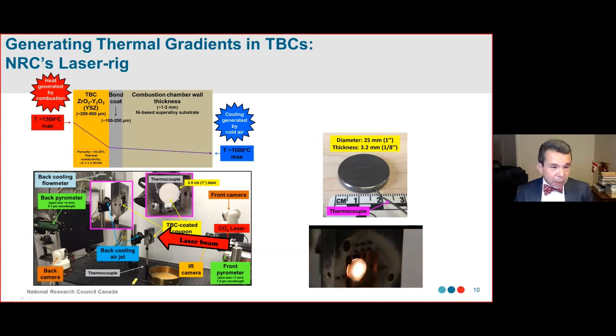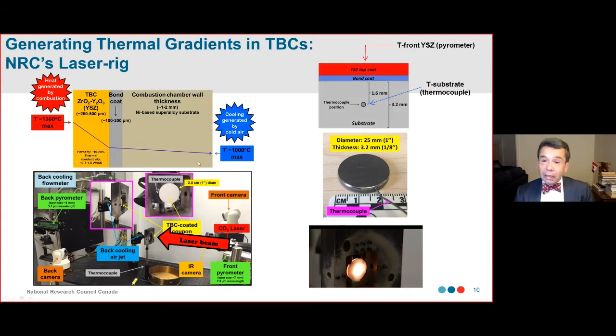And when you look at this picture, you can see there is a nozzle in here. This nozzle has compressed air at room temperature that keeps flowing over the backside of the substrate. This backflow basically cools the system, and therefore we generate a thermal gradient and we can study TBCs. How we study them: we measure the temperature of the YSZ or ceramic TBC using a pyrometer, and we measure the temperature of the substrate using this thermocouple here. This distance is about 1.6 millimeters, and I have been telling you that the thickness of these walls is between 1 and 2 millimeters. So measuring at 1.6 millimeters is basically the average thickness of the combustion chamber walls. So it's a good representation of the real system.